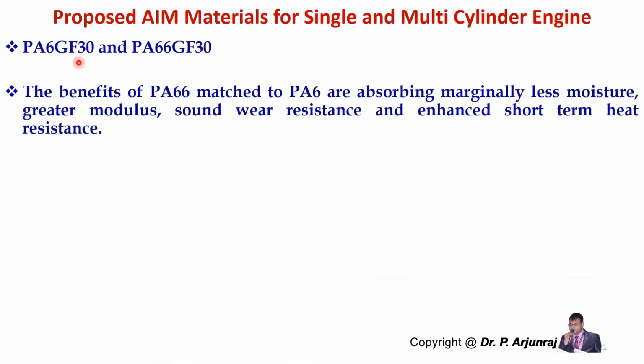Proposed air intake manifold materials for a single and multi-cylinder engine. So we have PA6 with 30% glass fiber and PA66 with 30% glass fiber. And the benefits of PA66 when compared to PA6 is that it absorbs marginally less moisture. It also has greater modulus, sound wear resistance, and short-term heat resistance when compared to PA6 glass fiber 30.